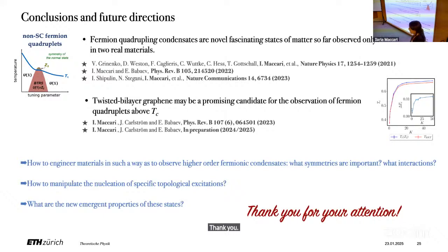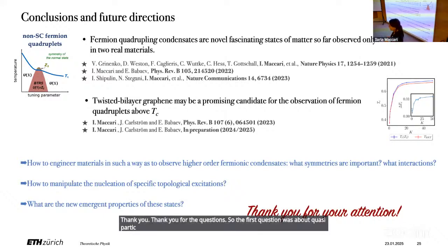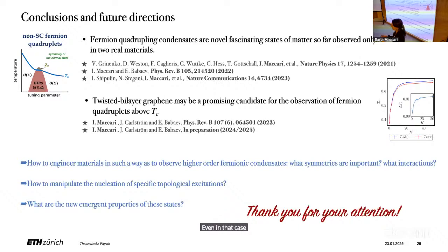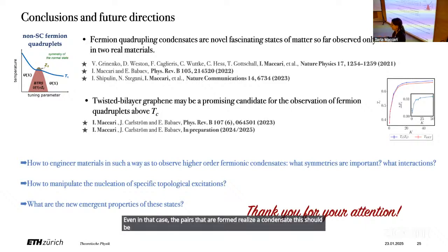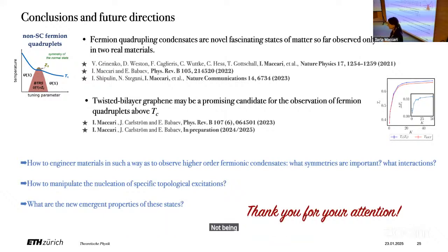Thank you for the questions. So the first question was about quasi-particles. Of course, yes, there are these kinds of fluctuations. So you can even see, already on the resistivity curve, that there is a region where you have this sort of Ginzburg-Landau paraconductivity. So you have this pair breaking effect. But still, even in that case, if the pairs that are formed realize a condensate, this should be enough to observe some signature. Of course, one should take into account quasi-particles when looking at properties in transport and this kind of measurement for sure, and see how they interact and scatter with this condensate. This is something that has not been explored so far, so it's a very interesting question.